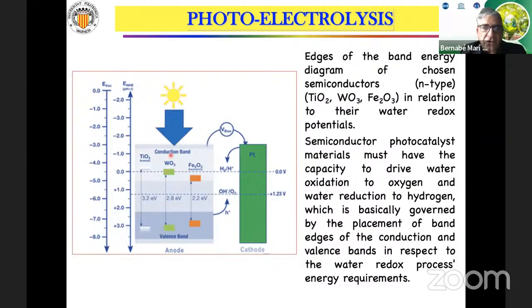Tungsten oxide was also used, but since 1.23 electron volts is enough, it is better to use a material with a smaller gap, for example hematite, iron oxide.